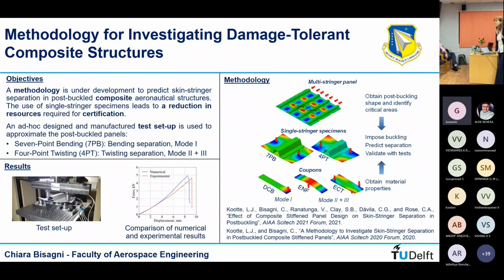Numerical models are along with the imperfection. Sometimes we put the imperfection, so we measure the imperfection, and then we put the imperfections inside. Depending on which phase we are. At the beginning, if we study a panel and we do not have it yet, we put an imperfection that are the eigenvalue, but when we have the panel, like in the test before and so on, we measure imperfection and we put them together. And you will see us in the next presentation.